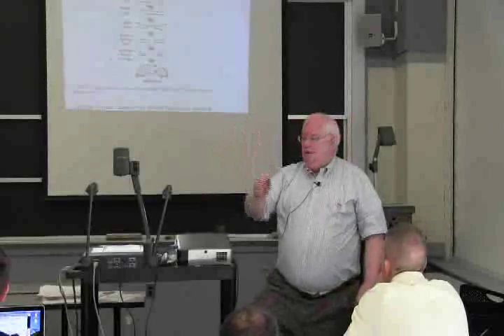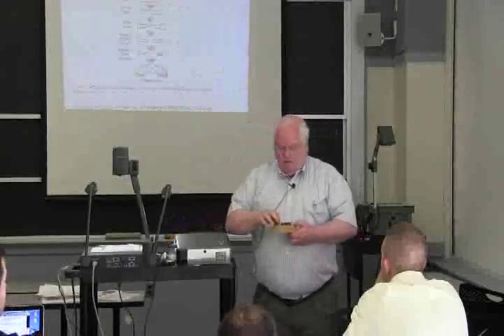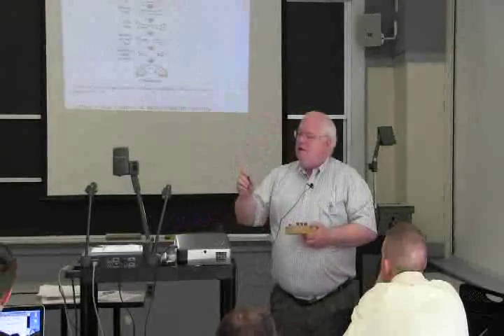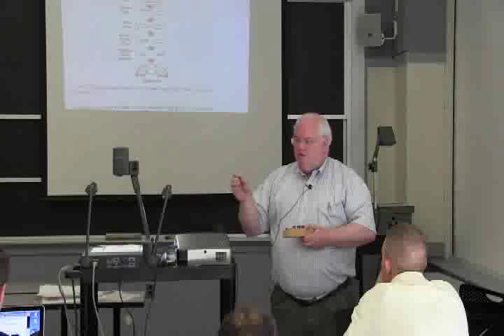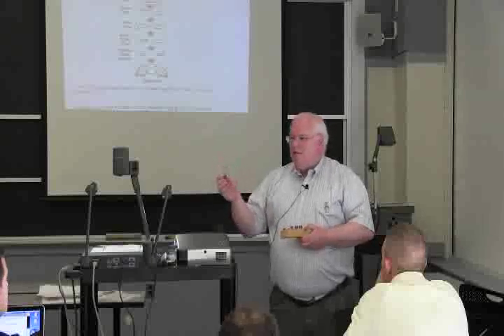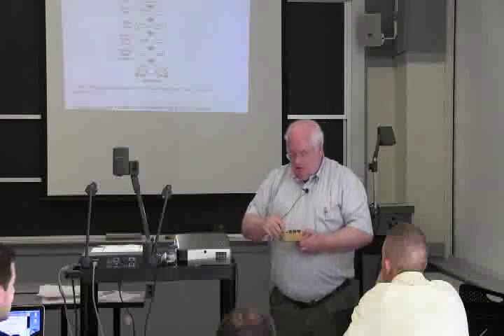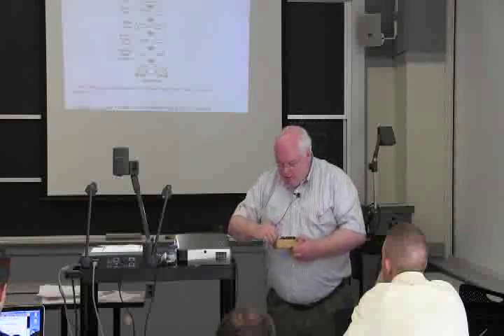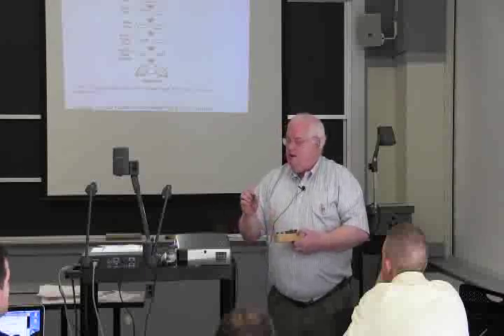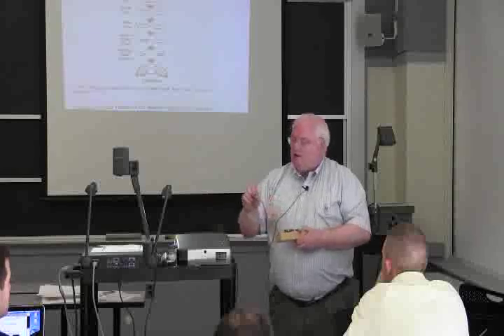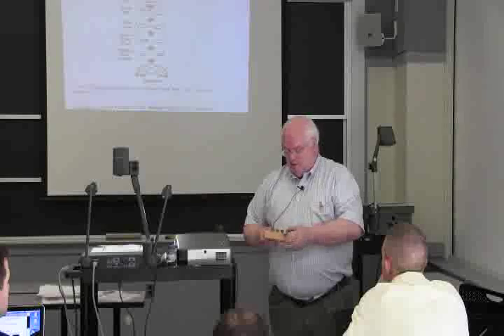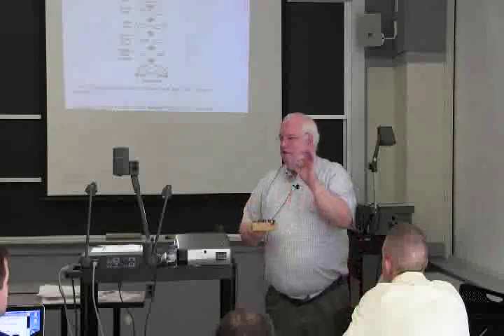This little chunk of metal, and you have to forge that. Now this is cold forge. The first one they size it, and it's got a little bit of a cone here, about a millimeter deep. Then they start to punch a hole in the bottom. They extrude a little hole, but they can't make it all the way because it would crack if they went any further. So then they do it again, they extrude it again. Then they put a head on it. Okay, then they have to, the one wasted piece of material, and is actually a little, they punch the hole out. Okay, and there's a little, I have the little hole there. It's underneath a little bit of tape. And then they do a finishing sizing. Then they knurl the threads on the outside. Then, or knurl the grip on the outside. Then they thread it on the inside, and then they plate it. So there are 11 steps of forging to make that part.